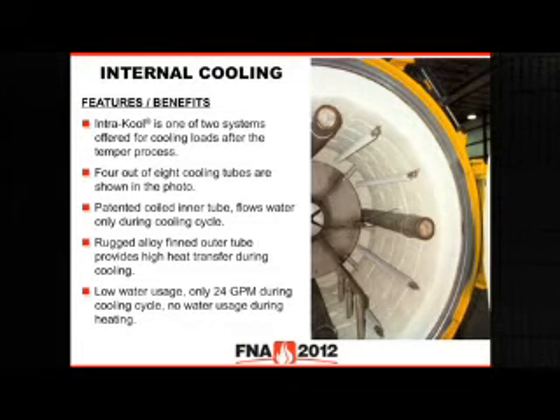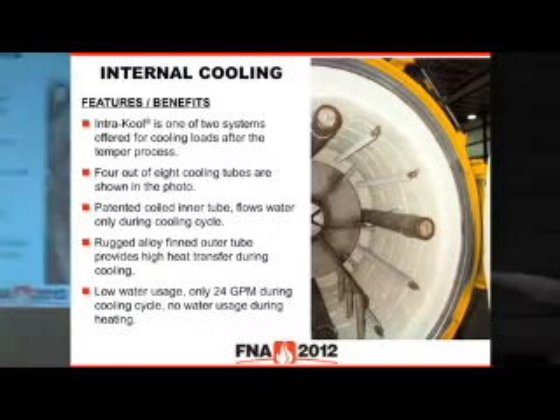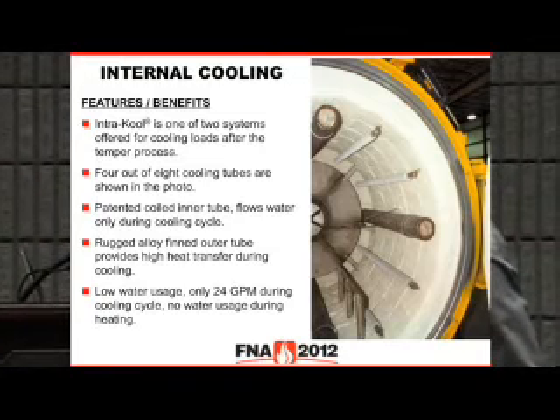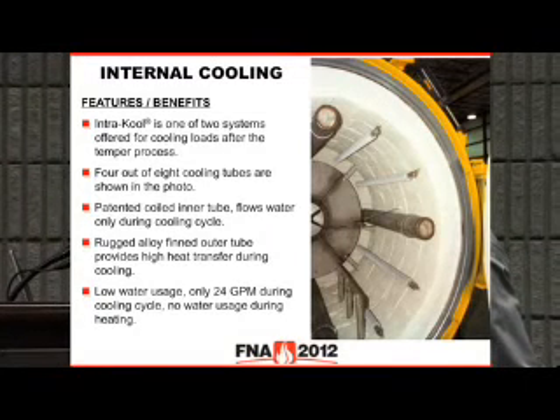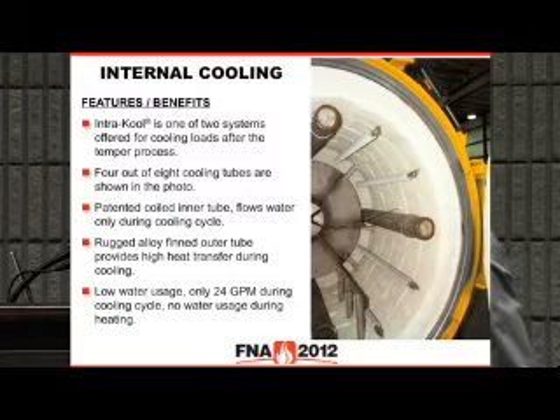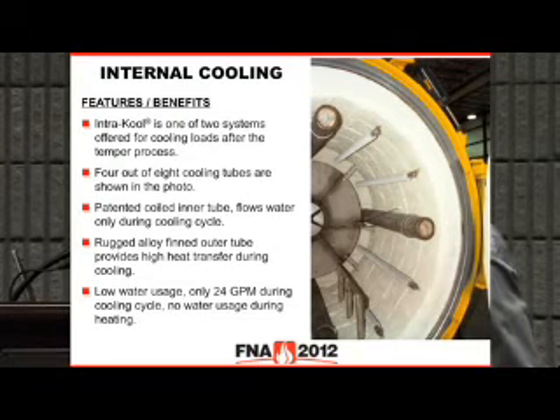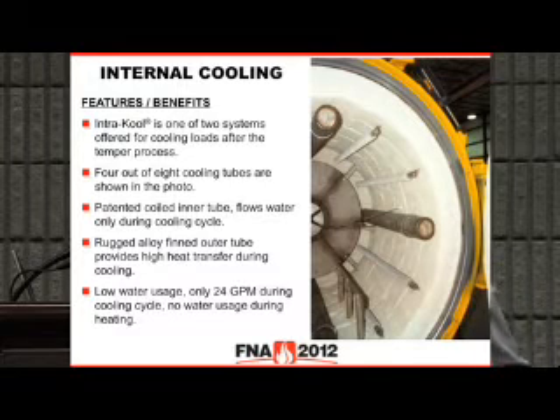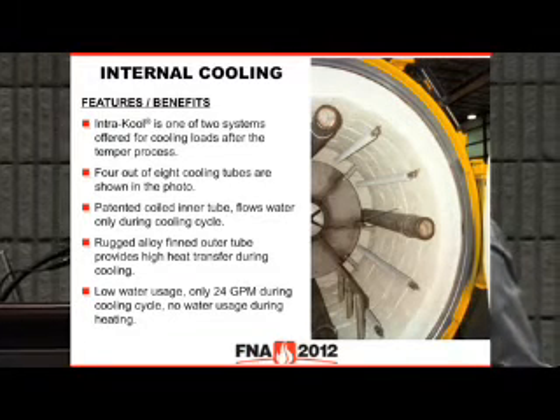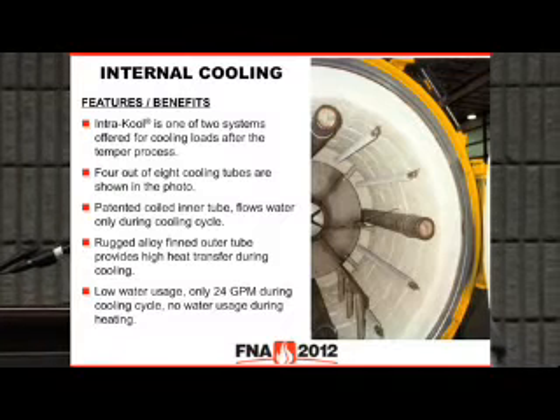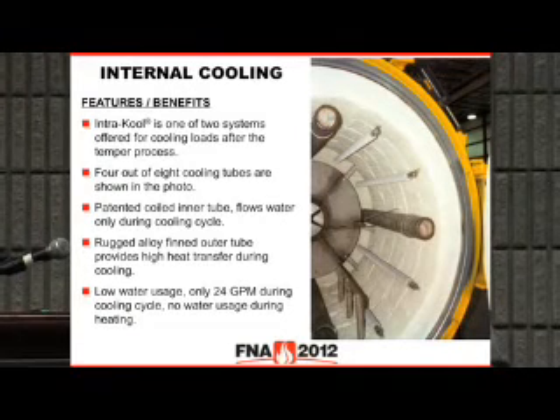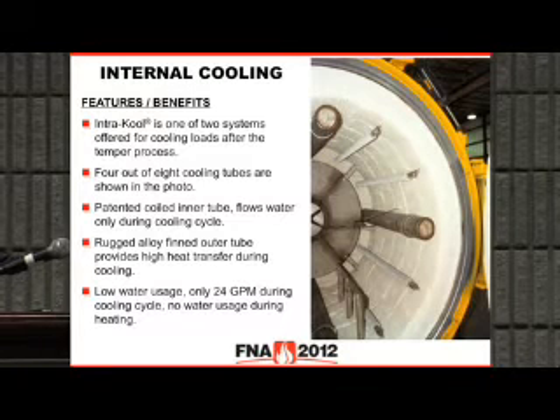Cooling systems. We've built a lot of these with what we call internal or intercooled cooling. We had 8 horizontal tubes which had a finning over the OD of the tube. And then in the center of the tube, which was actually a 330 type material, we had a stainless steel helix, and we would put water through that helix at the beginning of the cooling cycle. So we would run 8 of these traditionally, and it allowed the furnace to be smaller and simpler, and we've built a lot of them with this particular design.